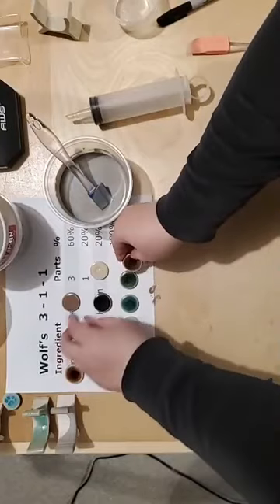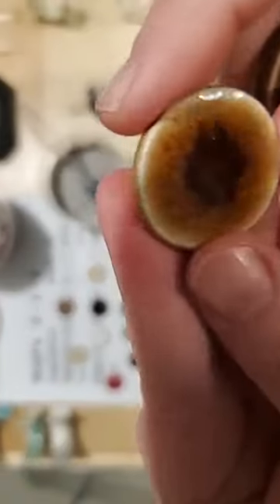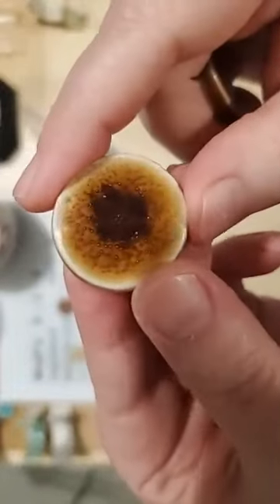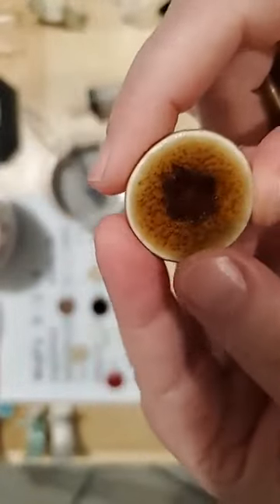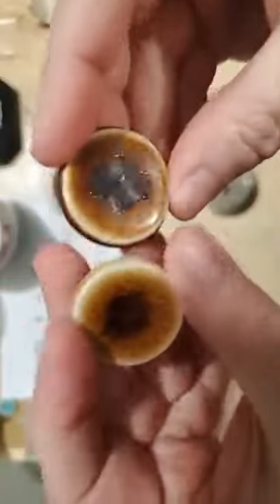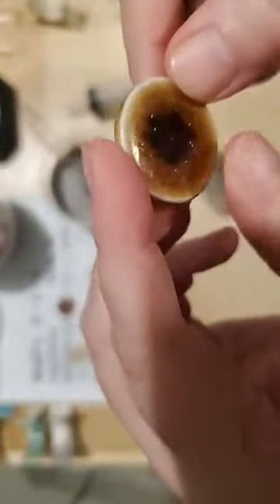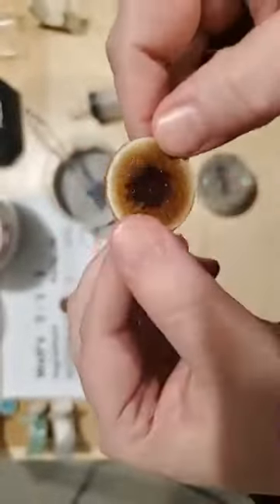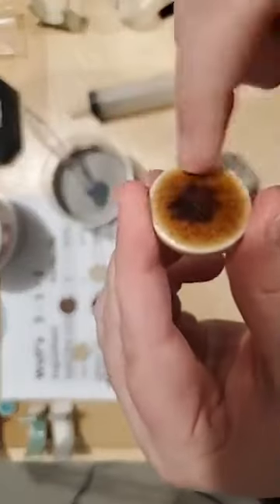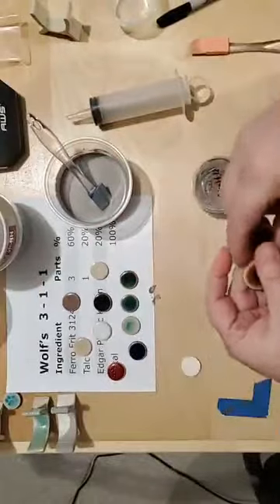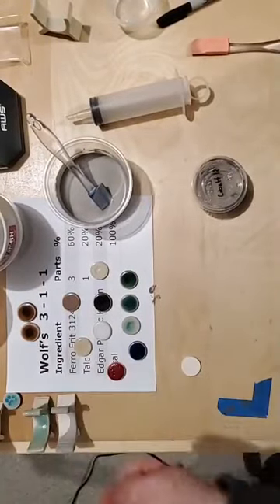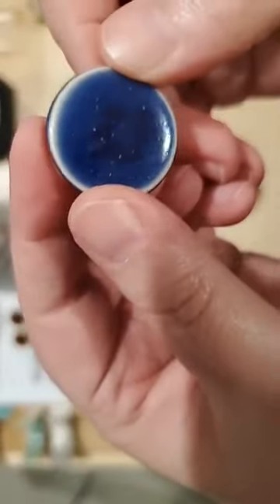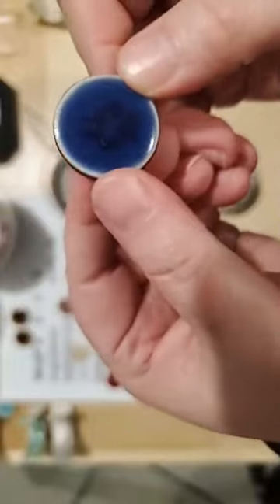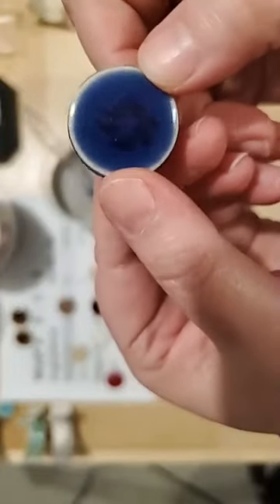In the manganese and the nickel ones, the manganese itself, as it was still boiling and whatnot, as it was firing, it just didn't have time to clear the bubbles. This was also a super fast firing in my little itty bitty test kiln, so I get a lot more bubbles in that. Cobalt, however, you can see there are fewer bubbles in this, and cobalt is a flux, and so it melted the glaze a little bit more, which allowed the bubbles to clear more.